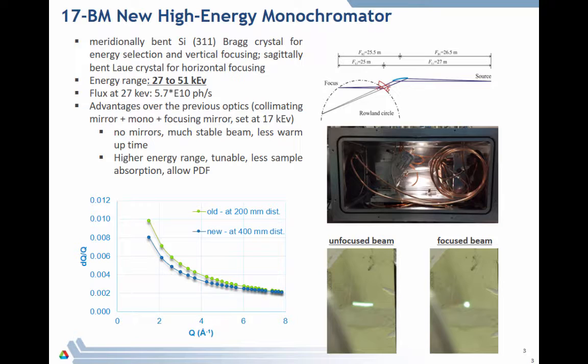Before, we had a mono which worked around 17 keV, and we had a quite large optical system. We had collimating mirrors, a double crystal mono, and then a focusing mirror. You can imagine a lot of motions and a long time to warm up the entire optical system. Now our beam, since we started running it, has been extremely stable, which is extremely important for in-situ measurements. So you want your intensity to be constant all the time.